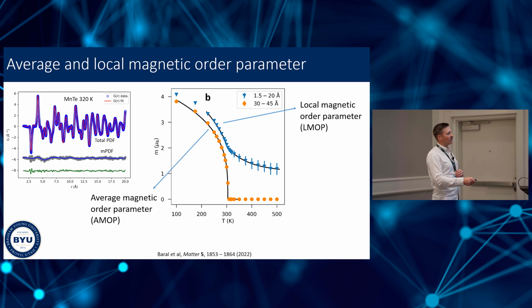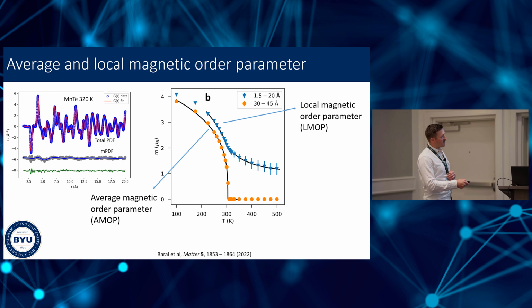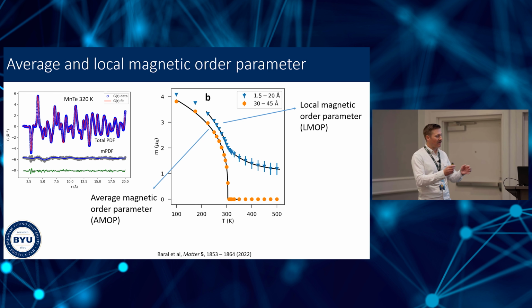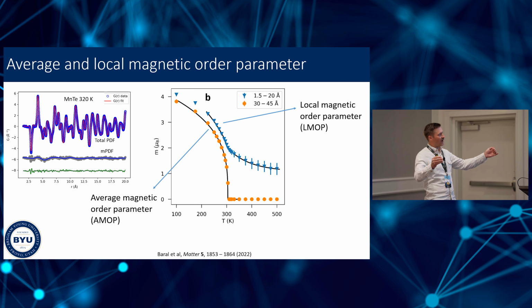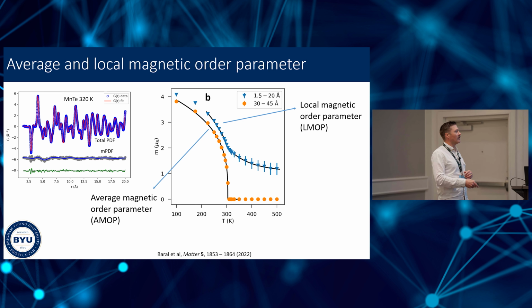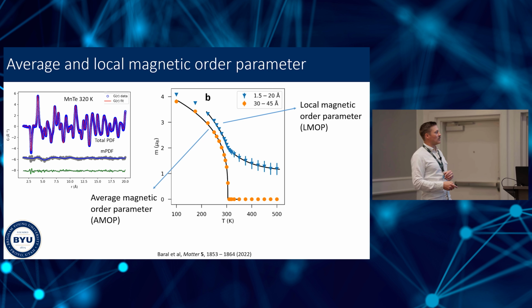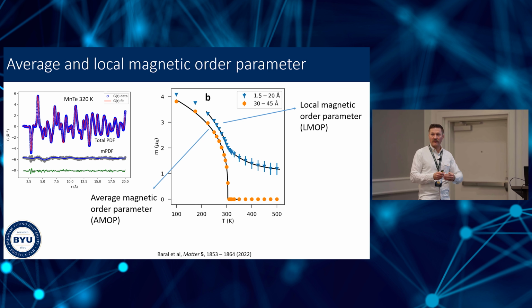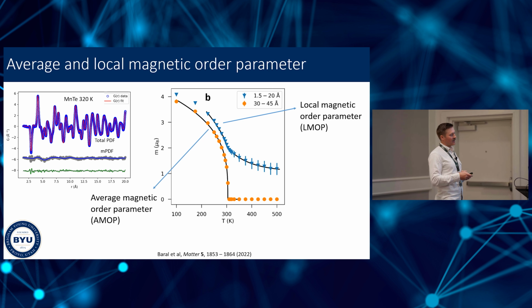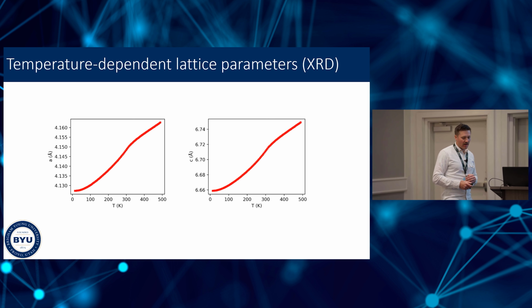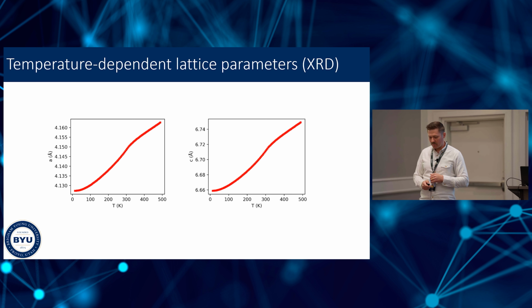The magnetic correlations are very much alive and well above the Néel temperature, with a significant ordered moment at the nearest neighbor distance of about 1 Bohr magneton. All right. So we have well-defined correlations that extend with a correlation length over a few near neighbors, with a net correlated moment of about 1 Bohr magneton, persisting well into the paramagnetic state. All right, what does this have to do with macroscopic properties?